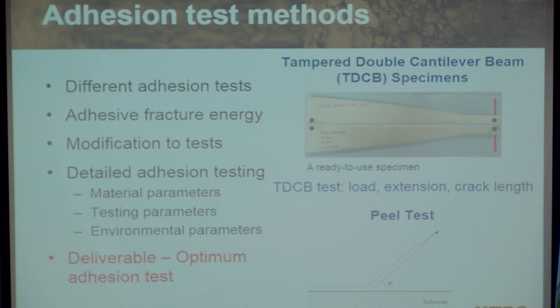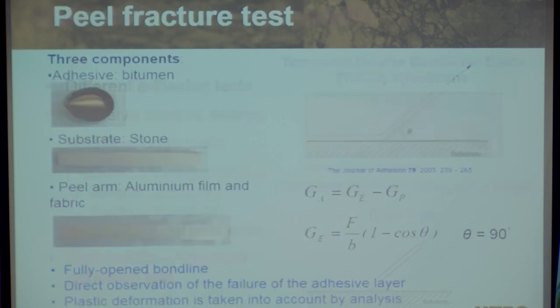It's a very simple geometry. You're essentially taking three components, an adhesive, in our particular case, bitumen. So in case of mechanical engineers, it would probably be some kind of epoxy resin. For us as pavement engineers, our main adhesive is bitumen. We've got a substrate. Again, if we were mechanical engineers, it would be some form of metallic substrate. Our main substrate is aggregate. And so we need to take a particular sample and convert it into an aggregate substrate. And then we need a third component, which is a mechanism for us to effectively debond that adhesive from that substrate. And we use something called a peel arm.